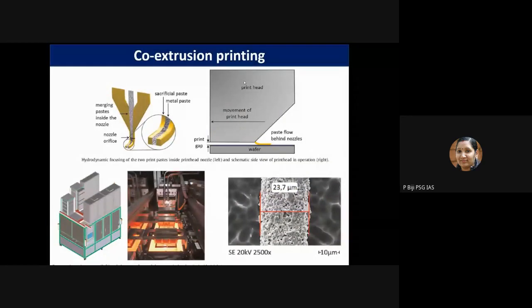So the next process is co-extrusion printing. In this case, the co-extrusion print head consists of a multi-layer nozzle assembly clamped between two sealing plate structures. Then a manifold plate distributes and splits two extrusion materials: a silver gridline paste and a sacrificial paste are used. Again, in this case, you can create high aspect ratio features very easily. Once the line is deposited over the wafer, the sacrificial paste prevents the lateral spreading of the metal paste. So that actually enables the aspect ratio. So this technology is also very good for creating high aspect ratio metal lines. But again, the problem is the cost for wider deployment.